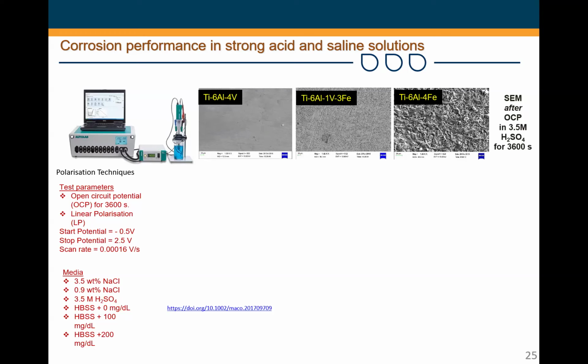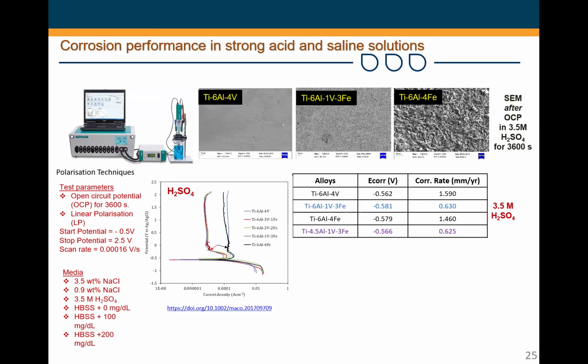But this can be misleading because the open circuit potential does not tell you the entire story. You need to know at what rate this material will rust or dissolve when you expose it to this environment. Mind you, this is not a physiological environment. This is an acidic environment, but we wanted to test the strength of the alloys we've developed first. And if you look in terms of corrosion rate, you will see all the alloys that have partial substitution of vanadium with iron, in these two cases, they have lower corrosion rate compared to when you replace the vanadium entirely with iron. Okay, and the corrosion rate of the Ti6Al4Fe and that of the gold standard material seem to be similar. And you can see the result here as well in terms of the linear polarization curve.